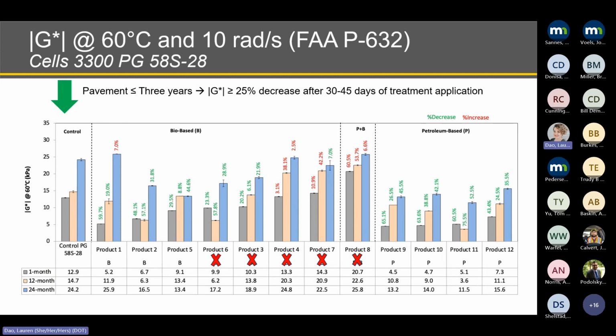You can see here on this graph, what is indicated in red means that we see a decrease in the stiffness of the treated binder compared to the control section. And what is in the other color shows that instead of a decrease, we saw an increase. And when considering the gray columns that are the data after 1 month of treatment being applied, we can see that some of the products that are marked with X did not reach this requirement of the P632 procedure, meaning that if we are supposed to classify these products considering the specification, they would be rejected because they do not decrease the stiffness of the binder at the specific window of 30 to 45 days.